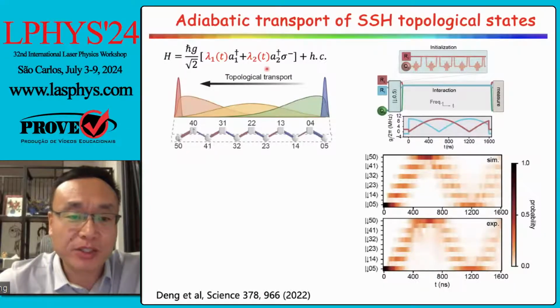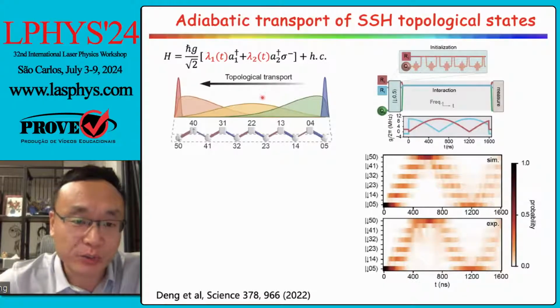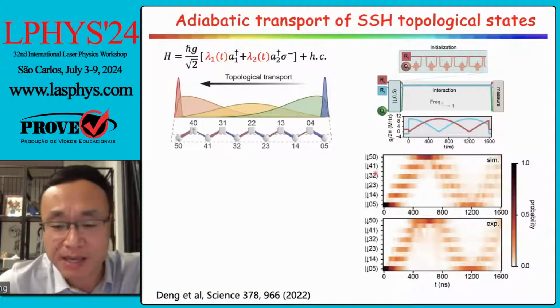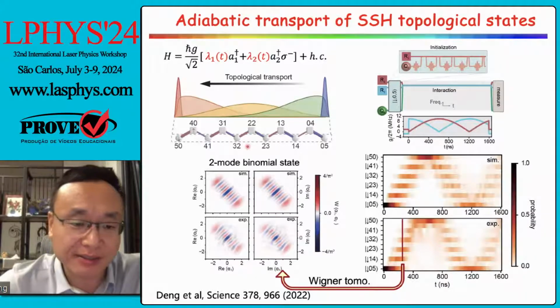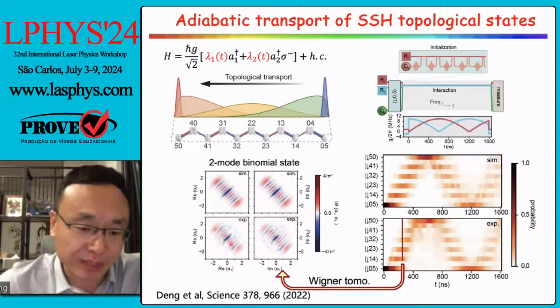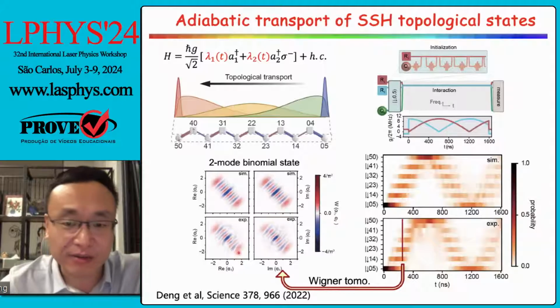So for the topological zero energy states of the SSH model, we can transport the edge state from one edge of the lattice to the other by changing the relative coupling strength between the two modes with the atom. And we find this experimentally: the initial state on the 0,5 side goes to 5,0. And in the middle, we can find it only occupies one of the sublattices. And we can make state tomography and find this is a two-mode binomial state, which keeps its quantum nature characterized by the negativity in the Wigner function.